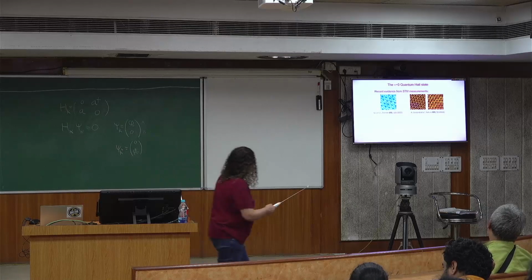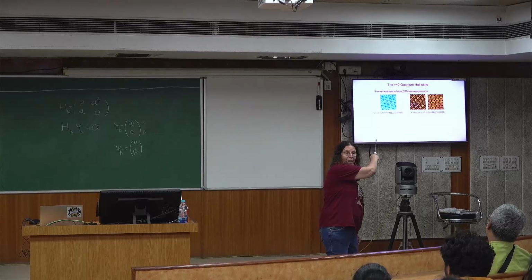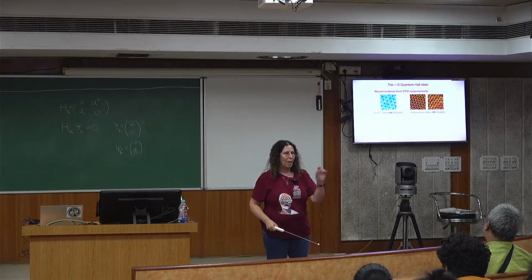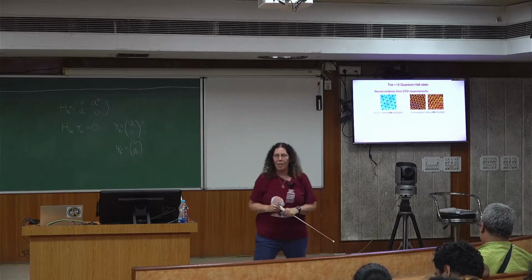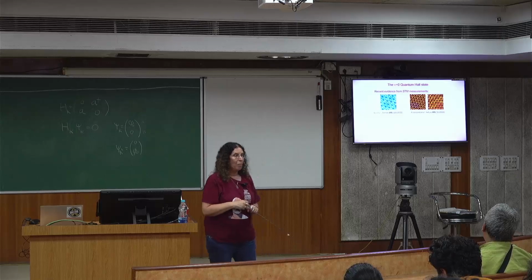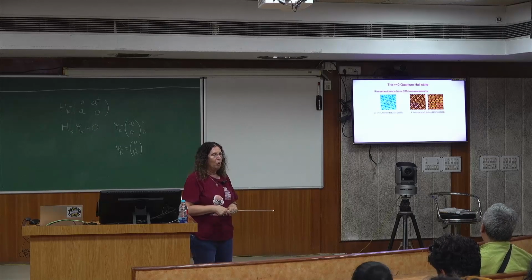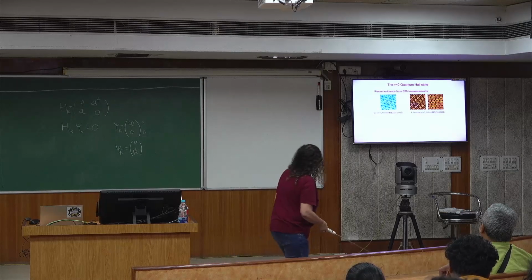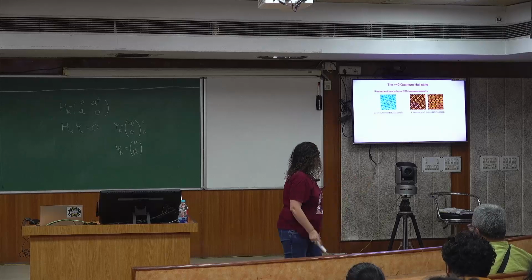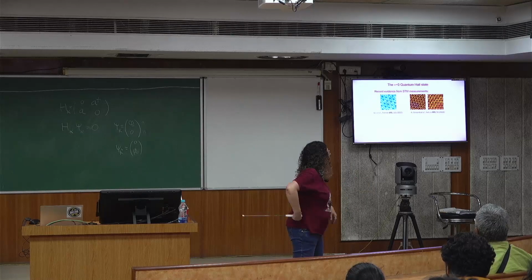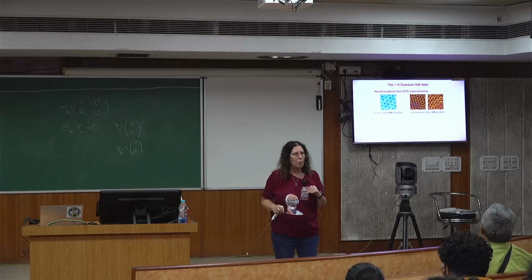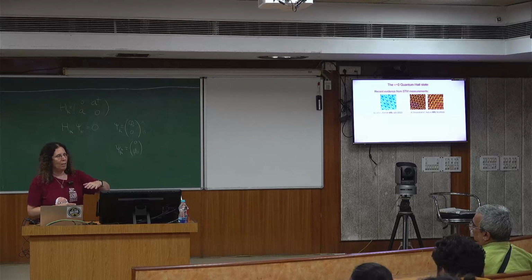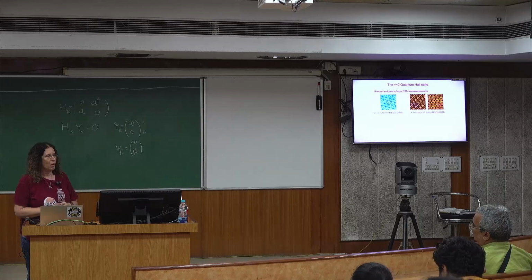But what I'm showing you is some figures from their papers, and in both of them you see something that looks very much like the Kekule distortion. At least the version of it that is bond ordered, a dimer crystal kind of phase, and that's the one that I told you is very exotic. And in fact, in Sacépé's group, they also see, by tuning the screening environment, the special thing is he had a substrate that is STO, strontium titanate.